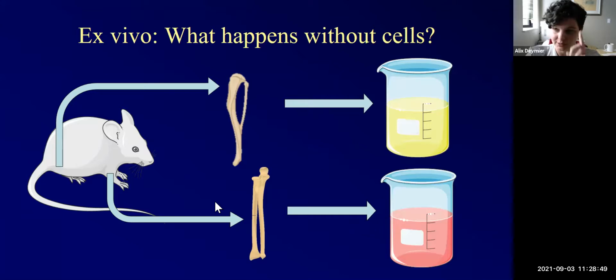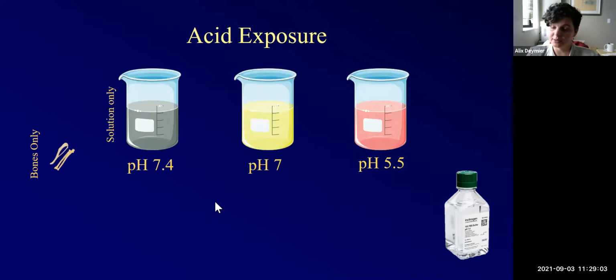So what are my conditions? This is important. Well, first of all, I'm going to do just bones. I need to have some sort of baseline. This is the composition, structure, and mechanics of the bones before any sort of acid exposure. Then I have just my solutions. The solution we selected is PBS, also known as phosphate buffered saline. It's a solution that represents body fluids in many ways, but it has lower levels of calcium and it's not super saturated. So it's not going to precipitate its own crystals, which is actually very important in these questions.